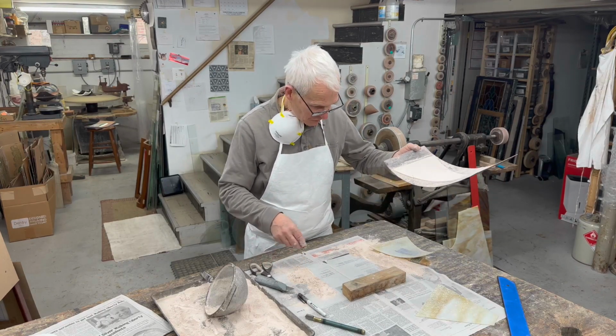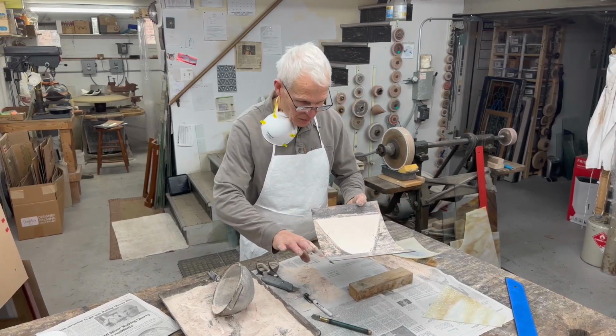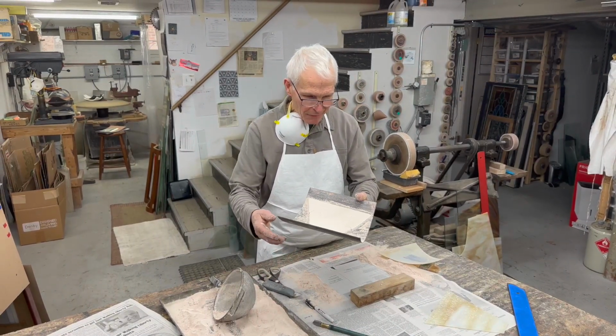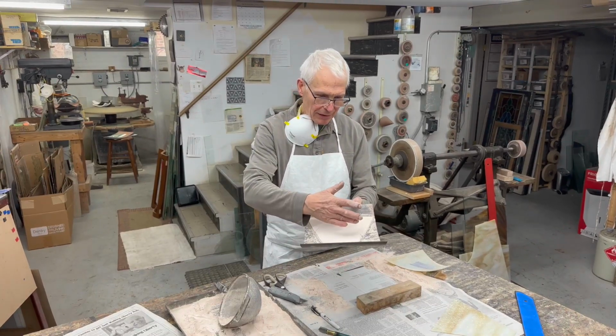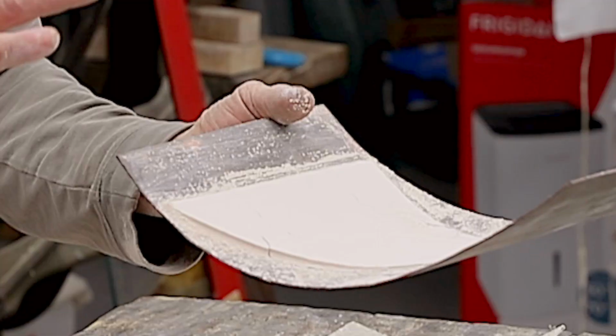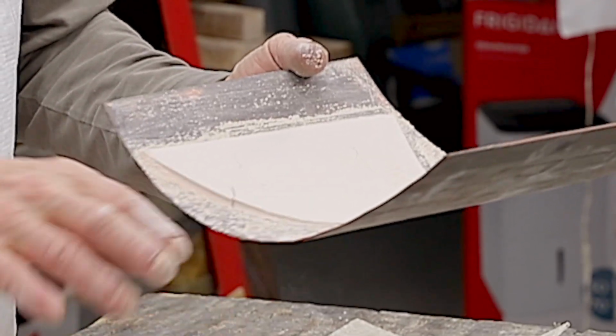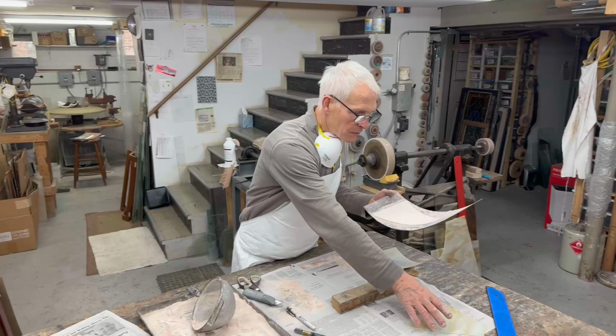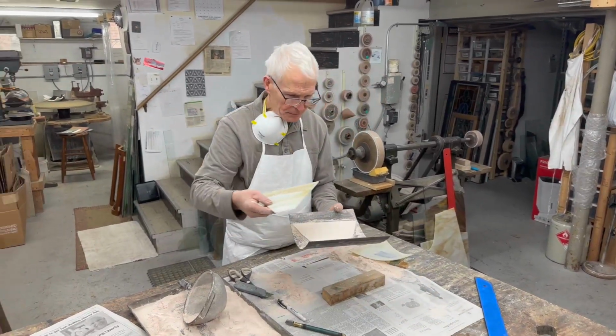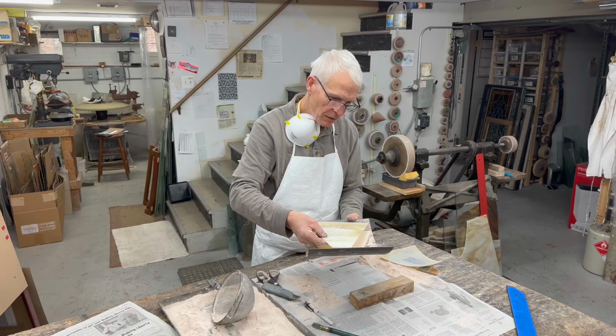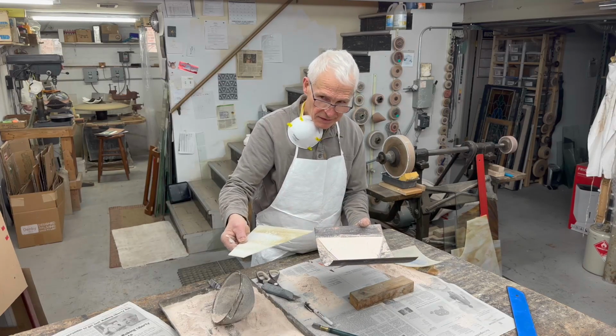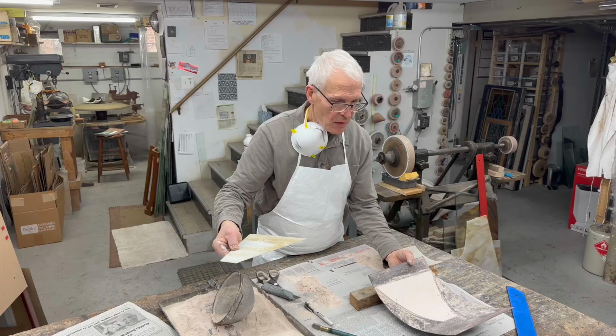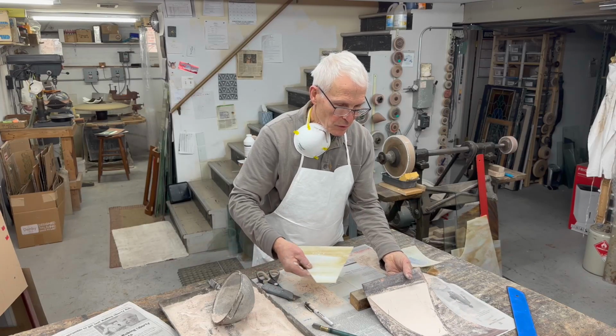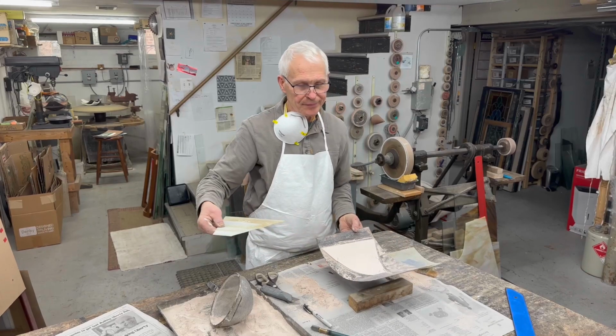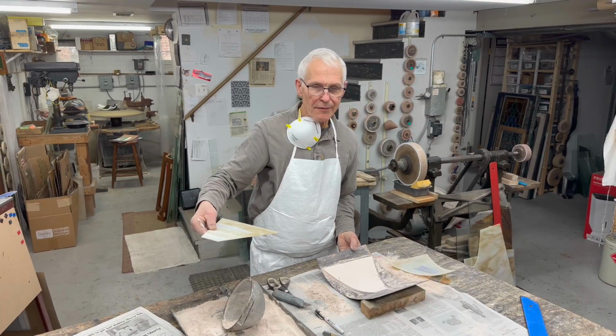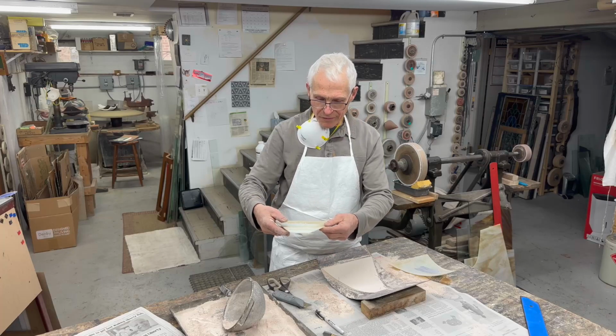Every time you do this, it's going to be a little different. But basically, even though there's this little bit of fissuring, this is plenty good enough for the process of taking this flat piece of glass, setting it over this, sticking it in the kiln, and heating it up. Something like this will probably slump at about 1125 Fahrenheit.